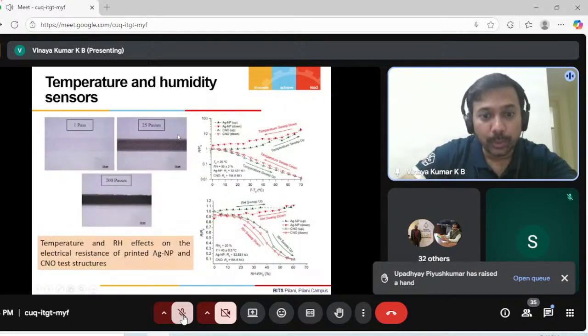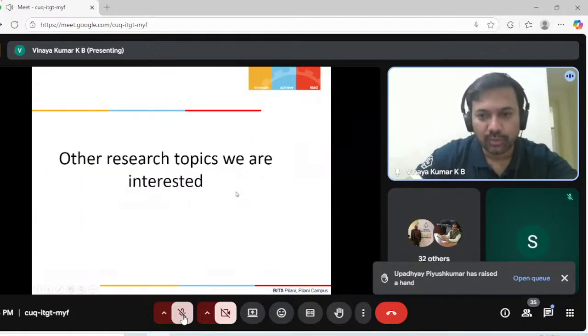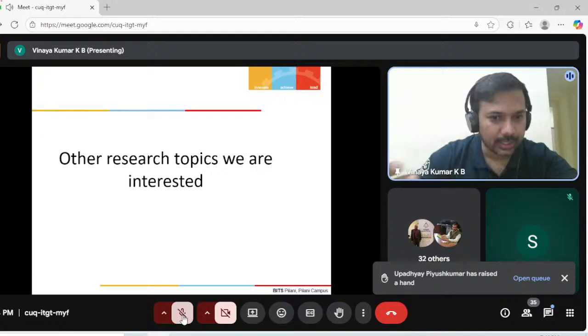So we were able to print humidity sensors out of it. These are carbon nano onions from one of our collaborators. We also worked on silver nanoparticles. CNO is carbon nano onion test structures for temperature and humidity sensors. So we were able to design and develop our own print head to print high viscosity fluids and nanomaterial based inks, and then realize different sensors out of it, right?